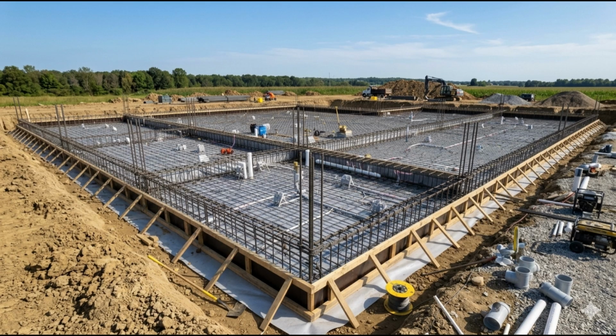A poker vibrator is a cylindrical device, typically 25 mm to 75 mm in diameter, containing an eccentrically rotating mass that causes the device to vibrate at high frequency when switched on. Inserted into fresh concrete, it causes the concrete to temporarily liquefy around it, allowing entrapped air to escape and the concrete particles to pack more densely. Proper vibration is essential to the strength and durability of concrete. The effective radius of vibration, the distance from the poker within which the concrete is adequately compacted, is approximately 4 to 6 times the poker diameter.